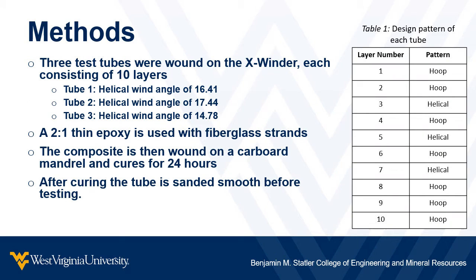The methodology for this project is to test 3 tubes that were wound on the X-winder, each consisting of 10 layers. The 3 tubes vary with helical wind angle, the first tube having 16.41 degrees, the second 17.44 degrees, and the third 14.78 degrees. The 10 layers consist of 2 hoop, then alternating helical hoop 3 times, and then ending in 3 hoop layers. A 2-to-1 thin epoxy is used with the fiberglass strands, and the composite is then wound on a cardboard mandrel and cures for 24 hours. After curing, the tube is sanded smooth before testing.